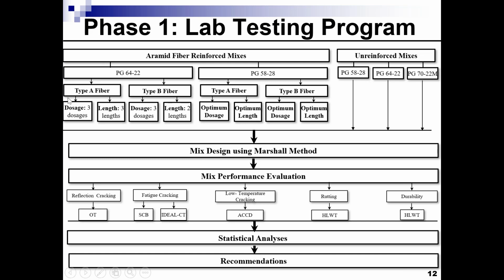So the focus there was to use two types of fiber. We're referring to them as type A and type B. And then we had different dosages and lengths. I'll be talking about the dosages and the length in the next slide. So we started with that. Based on that, we determined the optimal dosage, and we did a more limited study with a PG58-28, and we compared everything to the control mixes with the control binders, the PG58-28 and the PG64-22, as well as a polymer modified PG70-22M.